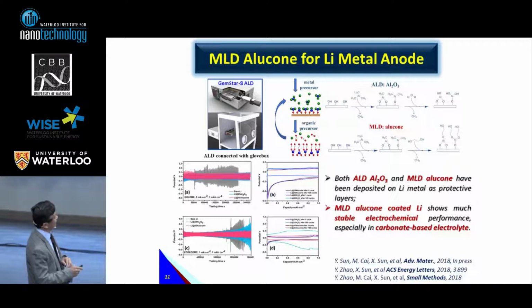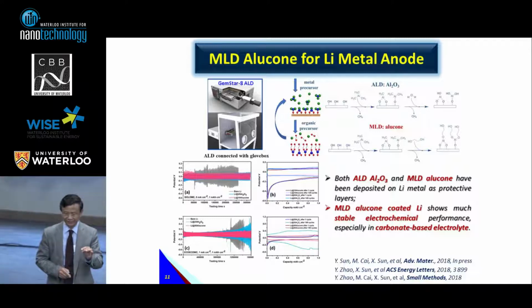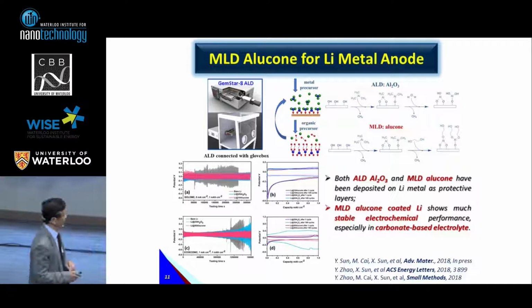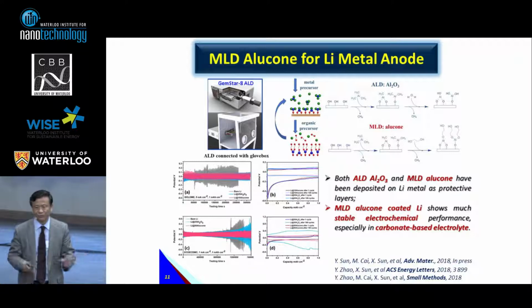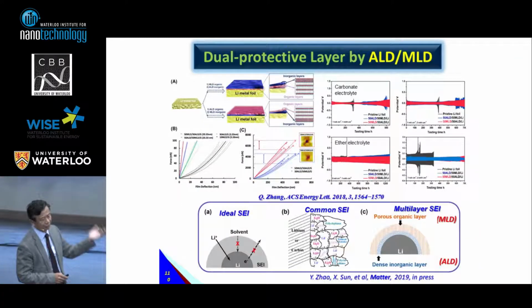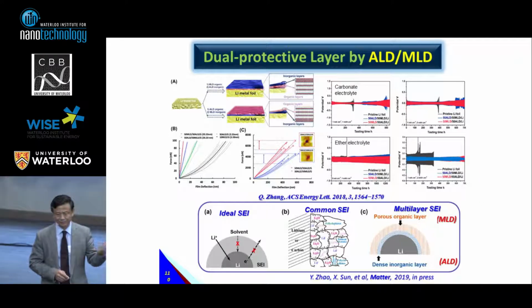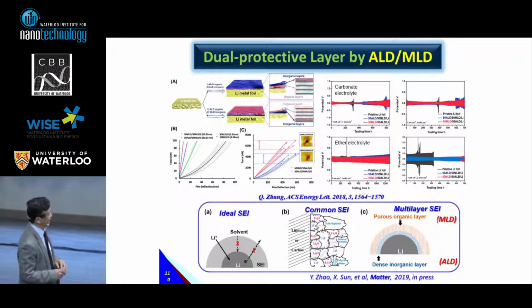That's why we're using ALD, MLD to address it. So firstly, we want to compare in liquid-based electrolyte how the interface coating can address the problem. Using ALD, MLD, you see the pink, compared with the no-coating one, the coated one is very stable in liquid-based electrolyte. And also recently we made a hybrid. The hybrid is much better because it has better toughness.